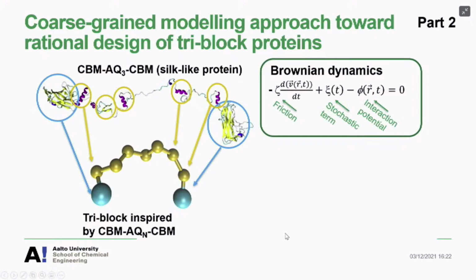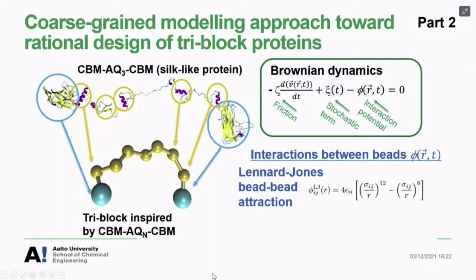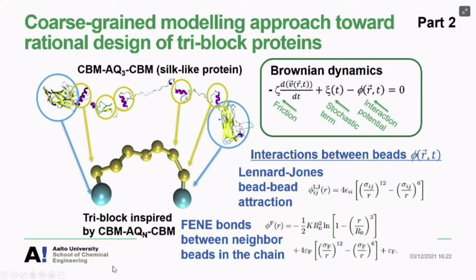Then we do Brownian dynamics. For those of you who are not familiar with Brownian dynamics, the method contains a friction term that's proportional to what is happening to the particle motion. Then there is a stochastic term, and then the interactions of the molecules, or the beads in the system, are captured by an external interaction potential. So crucial for this system, we need to have the interactions between the beads. Those are described by Lennard-Jones bead-bead attraction. So this is a simple Lennard-Jones bead model. And then to hold this protein together, we put FENE bonds between the neighboring beads in the chain.